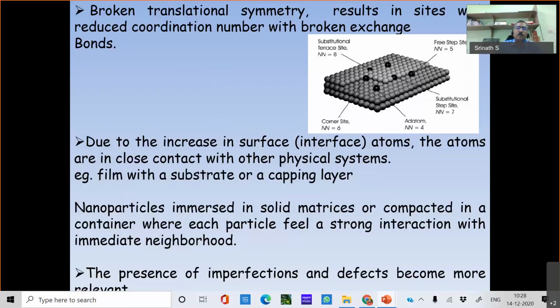So what we normally do is put what is called a capping layer. That means I'll deposit a film which is not reactive, like tantalum or platinum, or gold sometimes, depending on what I am actually interested in. So I can deposit another film as a capping layer so that my film doesn't get exposed to the air or atmosphere. But with the process, what is happening? The top layer of my film is now experiencing an interface with respect to this capping layer. So again, the potential is different.